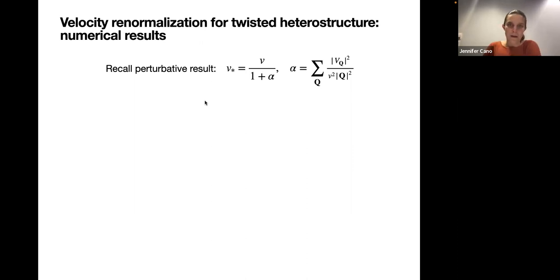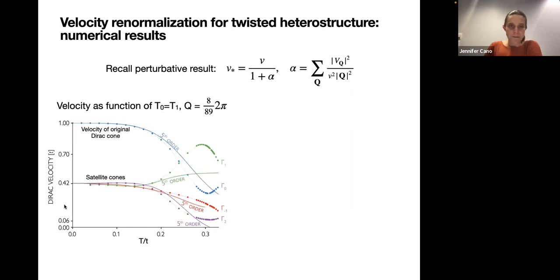And so the results that come out are as follows. Let me explain what this plot is. This is a plot showing the velocity of the Dirac cone as a function of the strength of the potential. Recall from the perturbation theory that I was just showing, that if the potential strength gets bigger, since it's occurring in the denominator, velocity should get smaller. And this is exactly what this plot is showing. These dots are all different numerical simulations as we're increasing the potential strength, and this solid line on top of it is our perturbation theory, going out to fifth order so that it stays valid for longer.